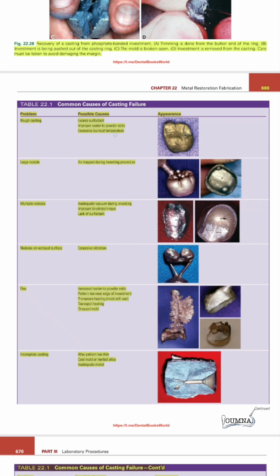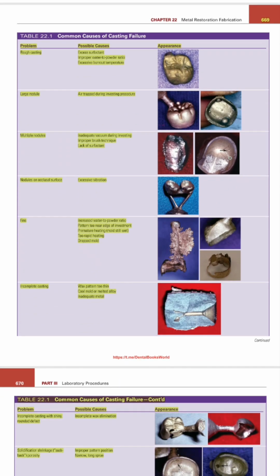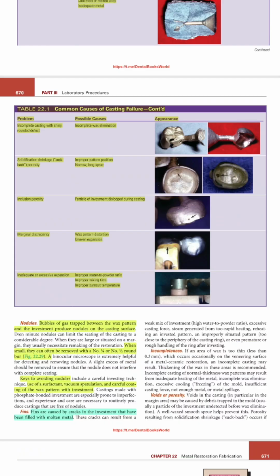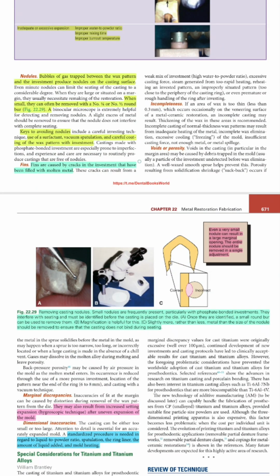If we had a large nodule, it is air trapped during the investing procedure. If we have multiple nodules, it is an inadequate vacuum during investing, and it can be removed by burr. If we got the fins, it is caused by cracks in the investment that have been filled with molten metal. If you got an incomplete casting, it is an incomplete wax elimination. The fins are caused by cracks in the investment that have been filled with molten metal.